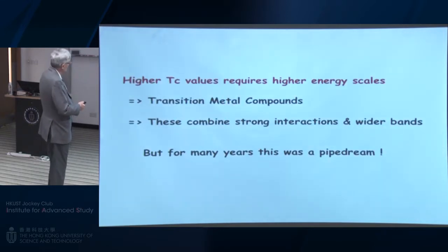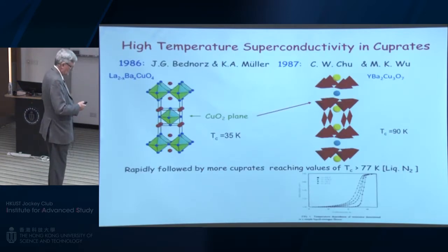So it's clear then what we need for higher Tc values: we need conduction electrons that move on higher energy scales. And for this, the transition metal compounds are the ones, because the d electrons on the one hand are partially localized, they have stronger interactions, but on the other hand, they're not nearly as localized as the f electrons, so we can combine strong interactions and wider bands. But for many years, this was simply a pipe dream, and there was no candidate for high Tc superconductivity. So this changed in the mid-1980s.